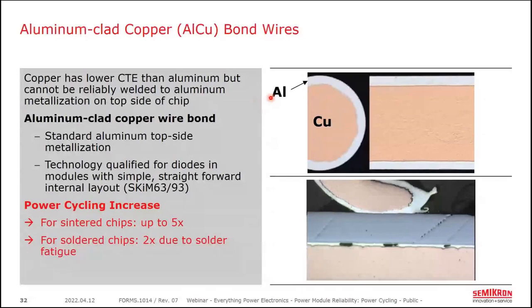Now, copper is difficult to reliably ultrasonically weld to a chip with that aluminum topside metallization because you need a little bit more pressure and you risk damaging the chip. And so the solution for us is to clad that copper wire with a thin layer of aluminum. So you get a wire that on one hand doesn't expand as much when heated, but on the other hand can still be welded to standard chips using standard production equipment. So we don't require a special copper topside metallization, and we can utilize the same bond wire equipment in our production line.